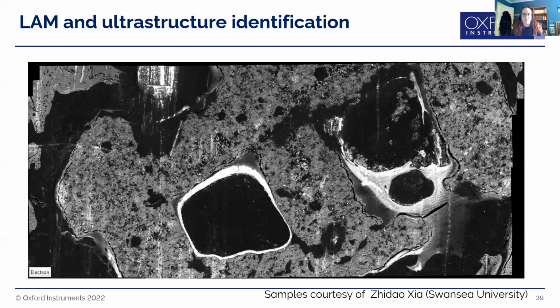So this is after 1 month of the implant being in place. We've got some bone tissue up here, and this is the implant. We've clearly got something which in the backscatter data is very intense. And this is actually a montage of 240 images. So these have all been acquired at much higher magnification, and we've montaged and stitched them together. Now, it's very difficult in this, even though we've applied some stains. So we applied uranyl acetate as a stain on this sample, and this sample is embedded in resin, and it's been cut and then polished. And you can see some of the marks from the polishing on here. But it was actually quite difficult to really see where tissue and cells had invaded into the sample.